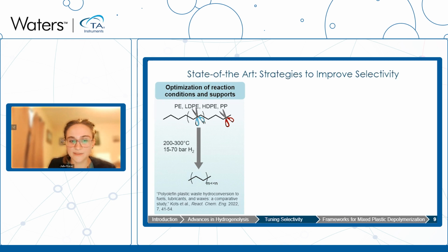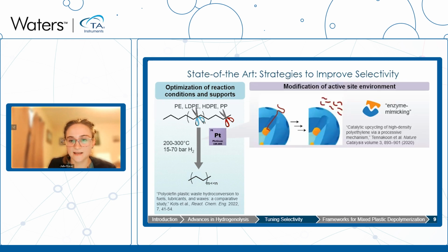And so some groups have been using platinum-based catalysts and this idea of enzyme mimicry to modify the active site environment of the catalyst to improve selectivity. And so this is a really exciting technique because you can avoid methane formation and really have more tunability as to what chain length of product you can get.